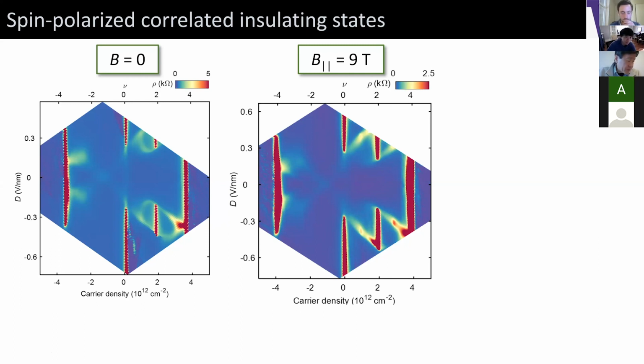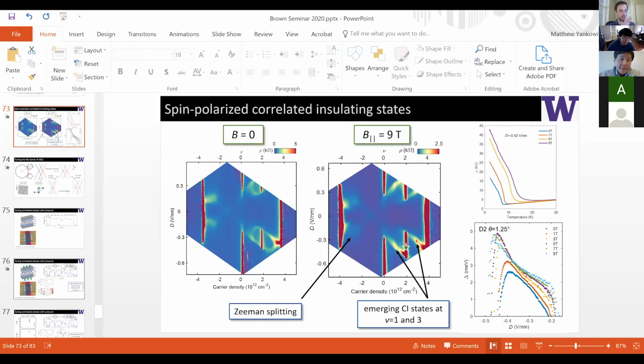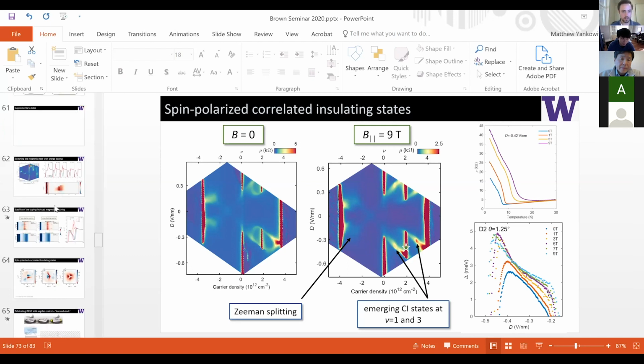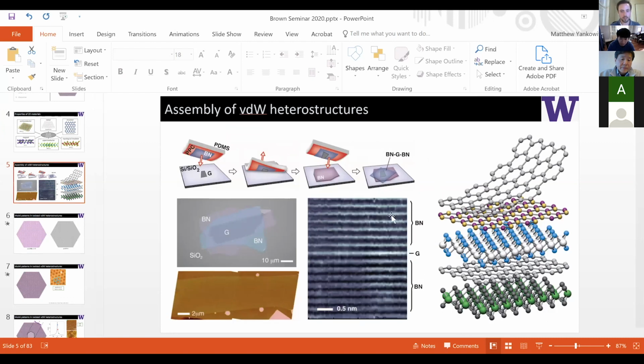Okay, a follow-up question: you use graphite and boron nitride as supporting substrates. What is the required surface smoothness or roughness of these substrates? Do they have to be atomically flat? They do, yeah. The magic of all of this is that you have pristine van der Waals interfaces between these crystals. In addition to providing a high quality substrate for the graphene, they also expel contamination and congregate it into pockets, which you can eject from the sample during device fabrication. So these interfaces are atomically precise and ultra clean. You don't see signatures of contamination in these cross-sectional TEM images. Without that, the mobility of these devices would likely be too low to see this physics.